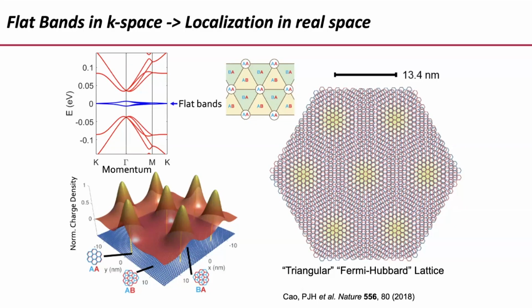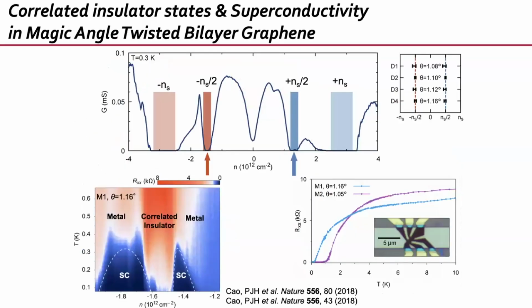But this was sort of the inspiration for a lot of the work that we were thinking about. Now, in 2018, my group discovered that when you put an integer number of electrons or holes per Moiré unit cell in the system, okay, you have correlated insulator states. And if you dope a little bit away from those, you get electrically tunable superconductivity. Yeah? This is something that was very unexpected and that drew a lot of attention. And I want to tell you a little bit now about some of the highlights of what has happened since. So we published this in 2018.